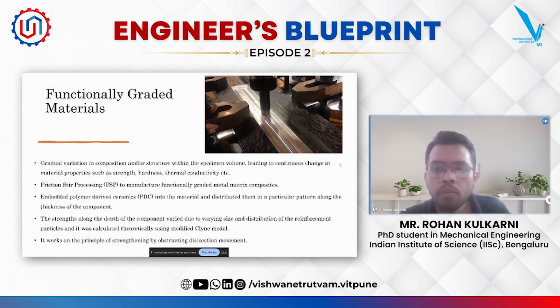So we distribute these polymeric particles within the material, in a particular pattern along the dimensions of the component, and then we do the pyrolysis. Pyrolysis is nothing but heating at the desired temperature. So once you do the pyrolysis, the organic part will evaporate and you get the metal matrix composites. So I developed one functionally graded material where I tried to vary the strength of the component along the thickness.